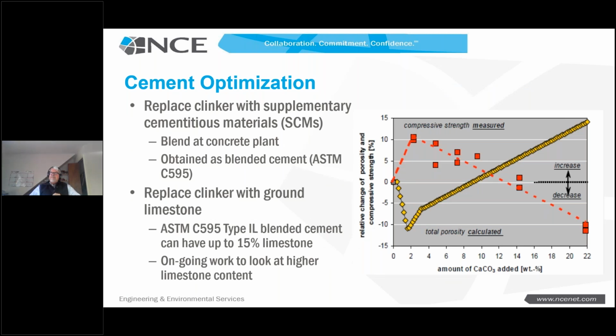When we move to cement optimization, this is about replacing that Portland cement clinker that we got out of the kiln with other things. The most common other thing is a supplementary cementitious material. In the US, that's most commonly fly ash, but it could be fly ash and other things. This can happen at the concrete plant, or it can happen at the cement supplier who does the blending.